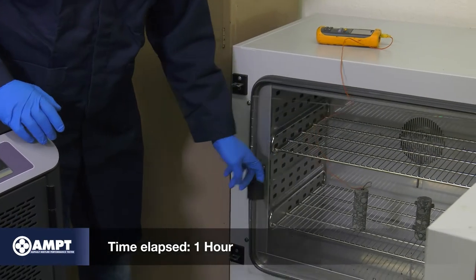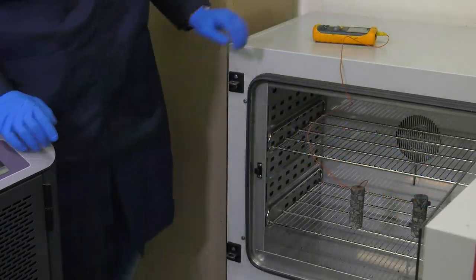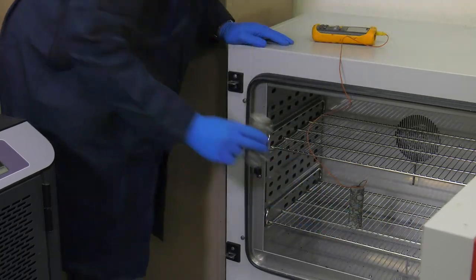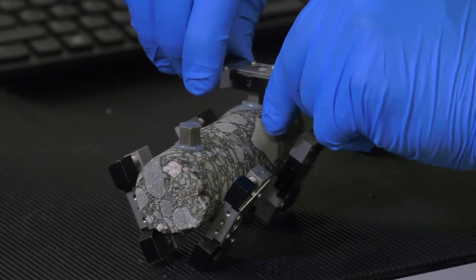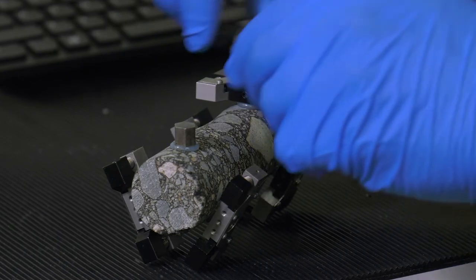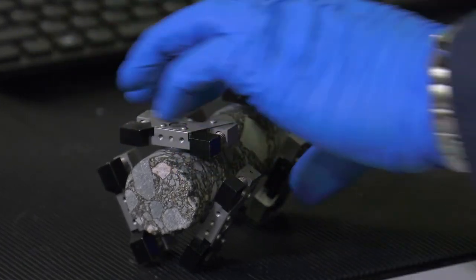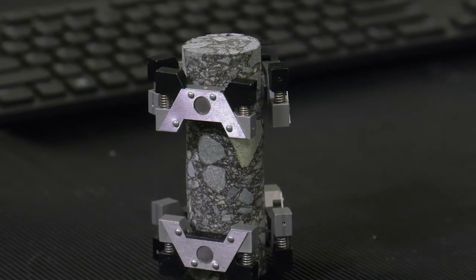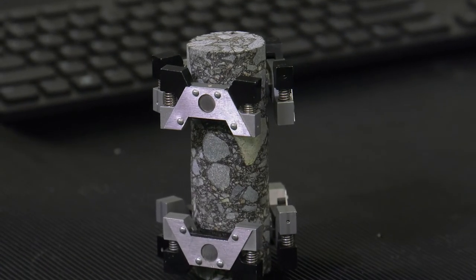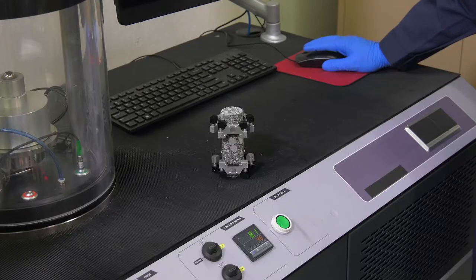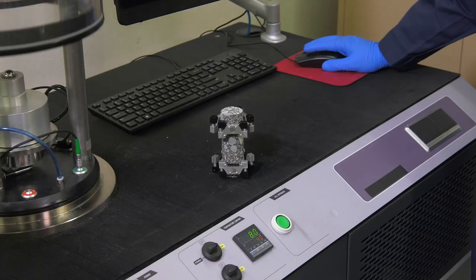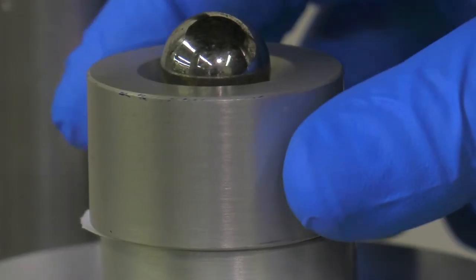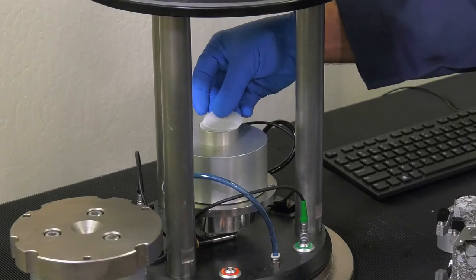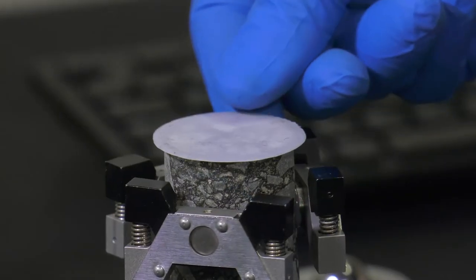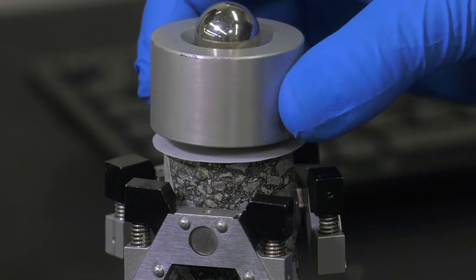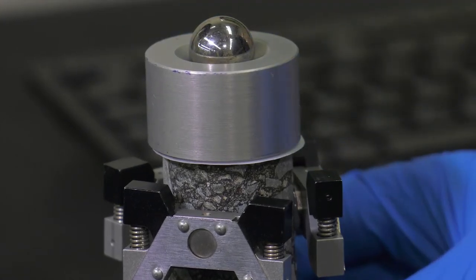Once the dummy specimen has reached the designated testing temperature, remove the test specimen from the external environmental chamber and attach the LVDT clamps. If multiple sets of LVDT clamps are available, they can be installed before placing the specimen in the external environmental chamber. Open the AMPT conditioning chamber and set up the test specimen. Remove the top platen and a PTFE sheet. Place the PTFE sheet on the top of the specimen and then place the top platen with steel ball.